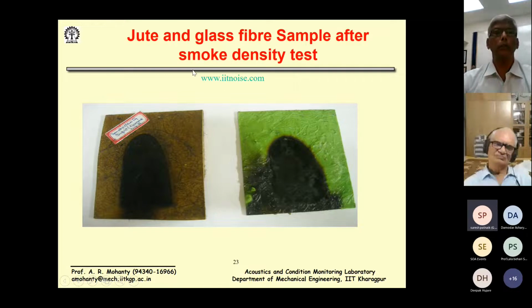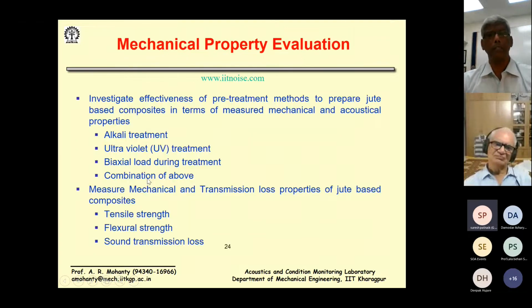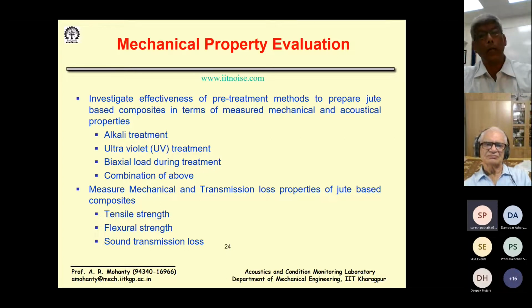Okay, and this is the smoke density test of the fiberglass sample and of the jute, just to give an example. And these were all done in our laboratories, be it in the chemistry department and material science department at IIT Kharagpur. But then it is not only the fire or the chemical, but comes the mechanical strength for a material which is being developed, because these materials have to be kept in places where they require an appropriate tensile strength, flexural strength, 3-point bending strength, and of course the transmission loss.